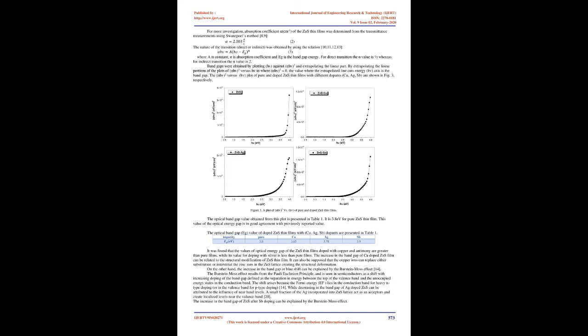The nature of the transition, direct or indirect, was obtained by using the relation (αhν)^n = A(hν − Eg), where A is a constant, α is the absorption coefficient, and Eg is the bandgap energy. For direct transition the n value is 2, whereas for indirect transition the n value is 1/2. Bandgaps were obtained by plotting (αhν)^2 against hν and extrapolating the linear part. By extrapolating the linear portions of the plots of (αhν)^2 versus hν to where (αhν)^2 equals 0, the value where the extrapolated line cuts the energy, hν, axis is the bandgap.